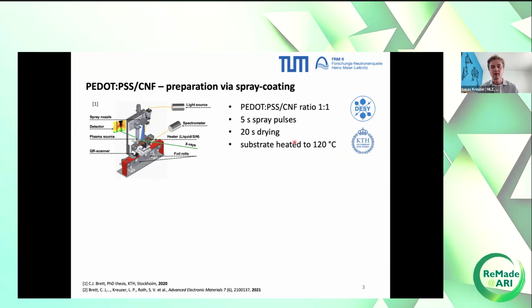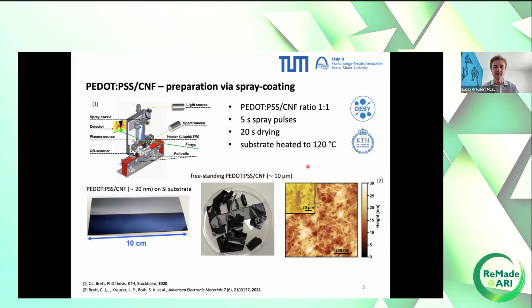So you have a certain time interval of spray pulses and a certain time interval of drying. And typically we spray coat on a heated substrate, a silicon substrate that is heated to 120 degrees. So the drying of the aqueous solution happens quite quickly. And the nice thing of this technique is that you can spray coat very thin films like these, around 20 nanometers on a silicon substrate. They are macroscopic in size, so 10 centimeters in length. The width is around 2 to 3 centimeters.